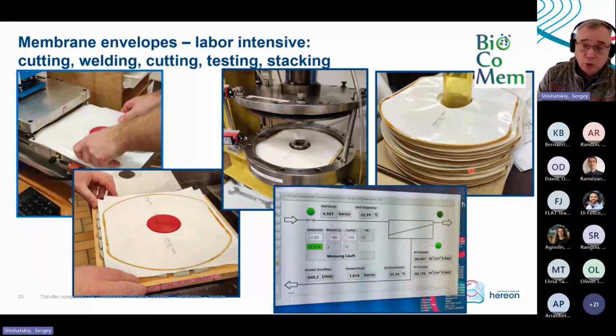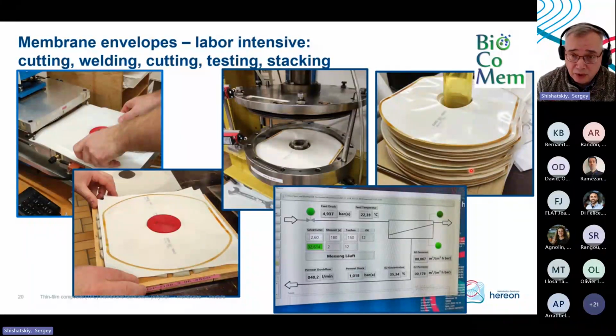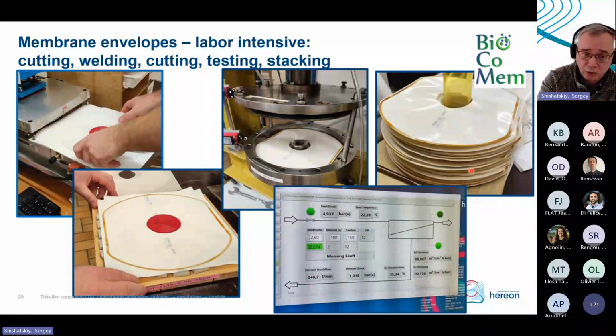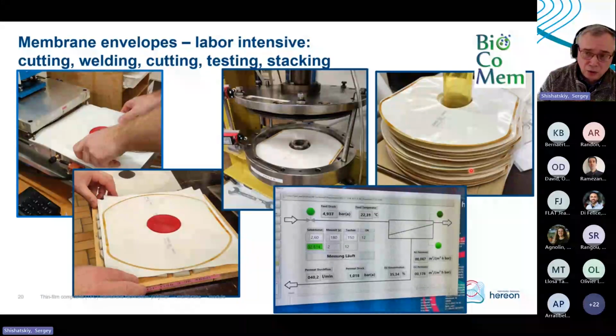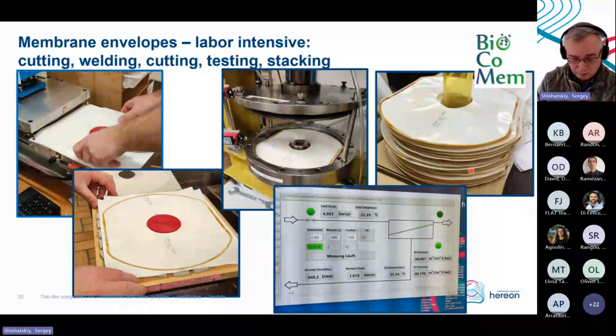And then we come to conversion of the membrane into membrane envelopes. This is very labor intensive because we need to cut a lot. We need to weld each envelope, and you need to take it into hands, so it's a labor cost. You need to cut it after the membrane envelope is formed, to a shape which is suitable for the module. Then you need to test it with oxygen and nitrogen for the quality of the envelope, and then you finally put it into the stack. And you collect the data for each envelope, and then you use this data to model the module.